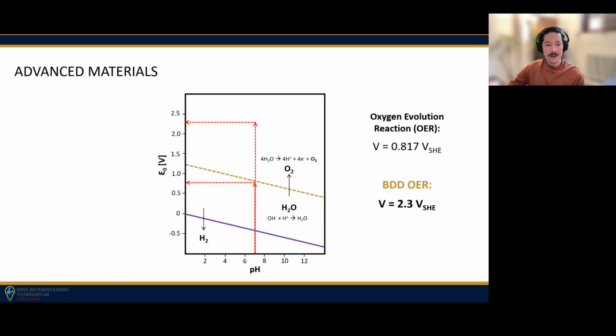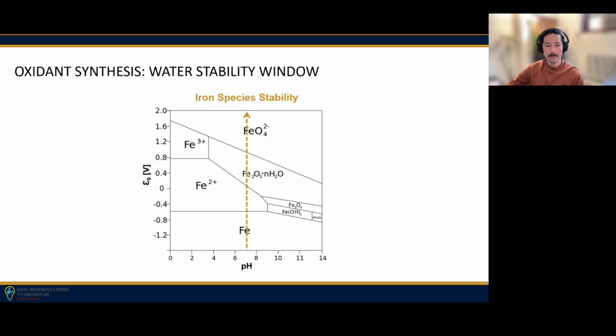So with standard electrode materials, our oxygen evolution reaction onset potential, the electrical potential at which this starts, is at 0.8 volts. However, in recent years, people have been making these advanced materials that have greatly increased our potential window. So using what are called BDDs, or boron doped diamond electrodes, we can increase that potential window quite a bit before we start making oxygen, which gives us a lot more space for the potential synthesis of ferrate.